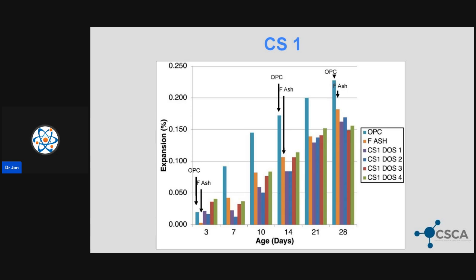And what we did from there is ran the ASTM C1260, which is your OPC mix, and then the 1567, which is your 20% class F fly ash mix. And then we ran mixes that had a replacement of cement with colloidal silica that matched up to that chart. What I'm showing you right now, CS1, was the smallest particle, and you can see it at all 4 dosages. We took this out to 28 days, and as you can see, starting from 3 days, there was some immediate expansion, but as we get past 14 and go to 28 days, that smallest particle, that 3 to 5 nanometer dosage, whenever we used it, there was a lower rate of expansion at our final 28 day, and pound for pound was much more efficient even when we went to our highest dosage.